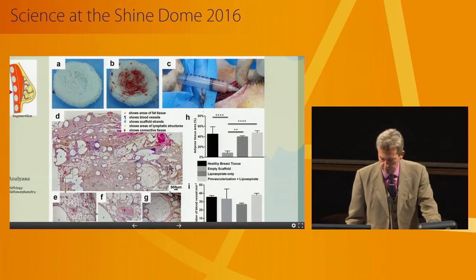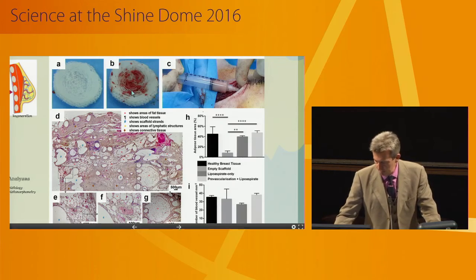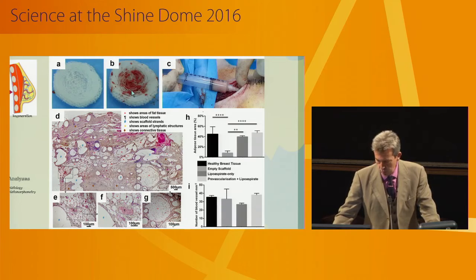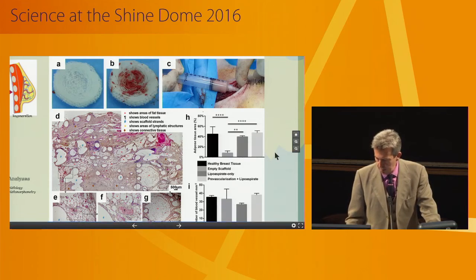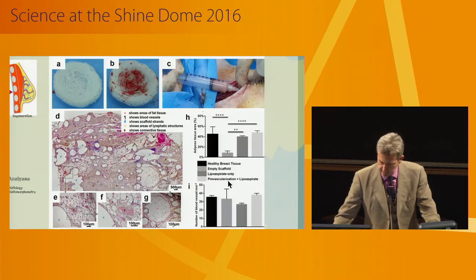This is after just 3 months, where you get very nice tissue formation through a scaffold which has a very large volume. Here we actually tested the smallest volume possible, which was only 20 milliliters of fat tissue in a scaffold which had more than 150 milliliters total volume. And in the analysis you see that we get much better results when we do this delayed injection of the fat tissue.